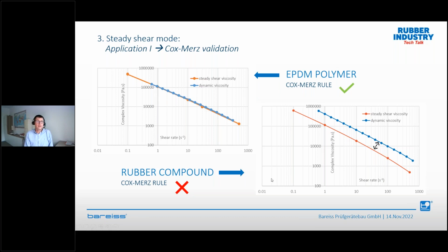When you go to a rubber compound, the Cox-Merz rule cannot work anymore because it's depending on fillers. So, for example, here, if you use the dynamic viscosity of a rubber compound, it's the blue curve. If you run a steady shear viscosity on the rotation, which is close to the reality of what happens in your machine, the viscosity is on a completely different level. And for example, if you would like to use something for simulation and you would give somebody the dynamic viscosity, it will definitely fail. He will have no chance to simulate the process. So dynamic viscosity is not able to support simulation. That's important. So you definitely have to go to this steady shear viscosity.